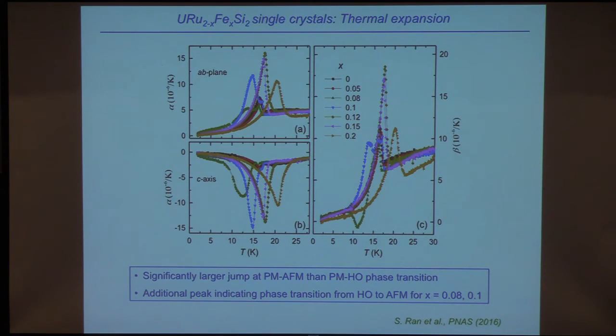So, then you can do thermal expansion measurements, which is where Quantum Design came in with some equipment that they developed. This is the thermal expansion in the AB plane. This is along the C-axis. And again, you see a lot of features. You can then deduce from this the volume thermal expansion shown right here. I'm not going to go into the details, but for some of these transitions, at 0.08 iron concentration, X, and 0.1, you actually see two transitions that are indicative of going from the paramagnetic phase to the hidden order phase and then into the antiferromagnetic phase.